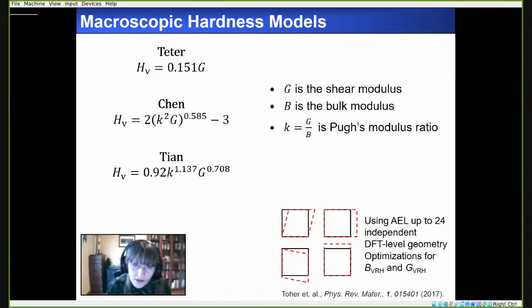There are also macroscopic hardness models available, where they employ either the shear modulus or the bulk modulus to estimate hardness. However, the problem with this is that determining these moduli from first principles, you might need up to 24 independent DFT type calculations, and so getting these estimates can be very computationally intensive.